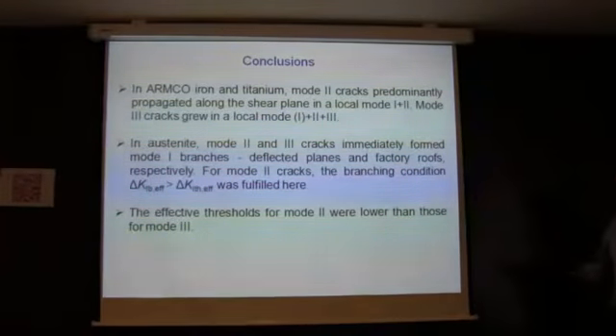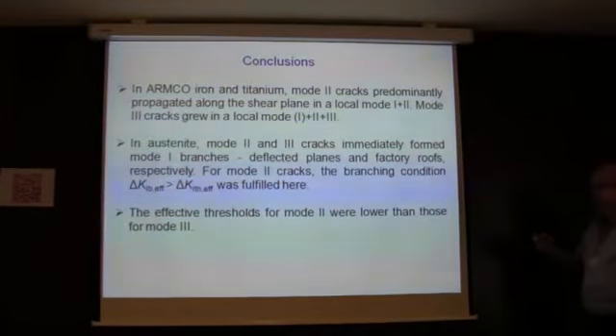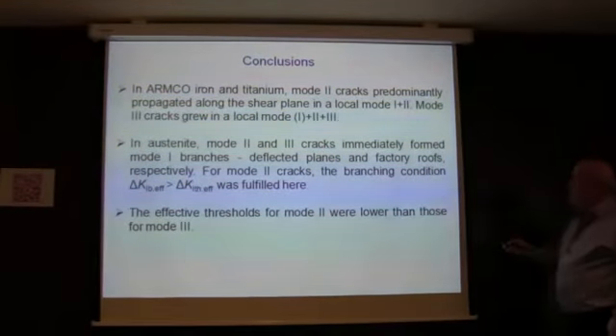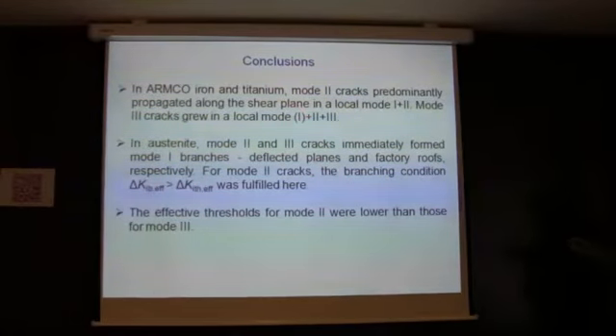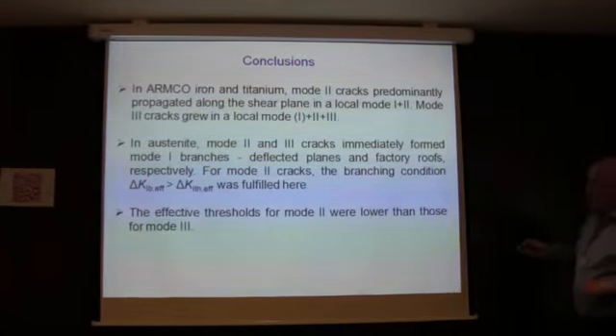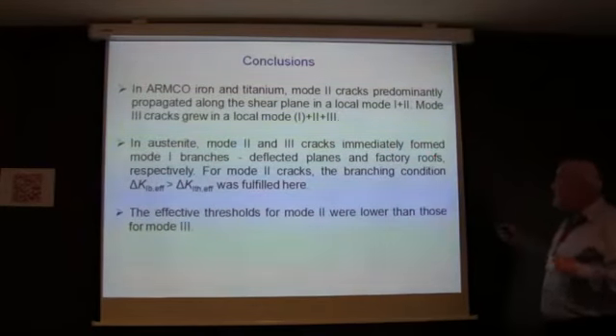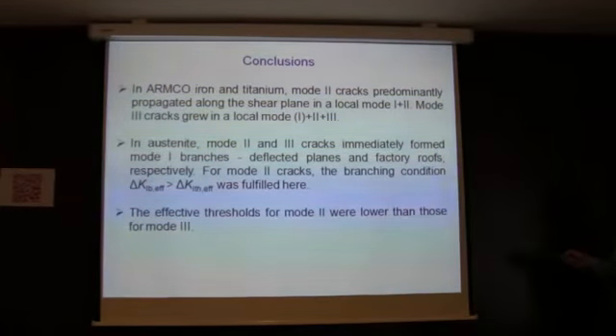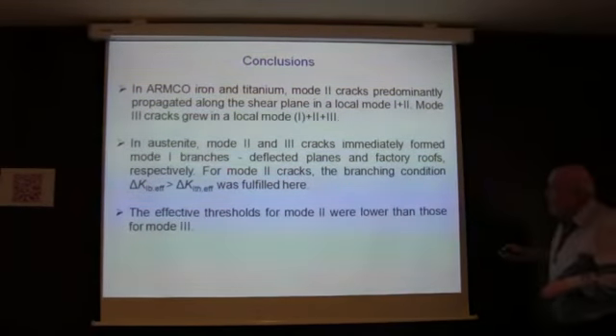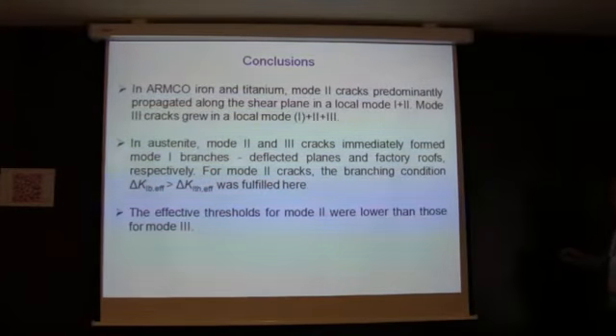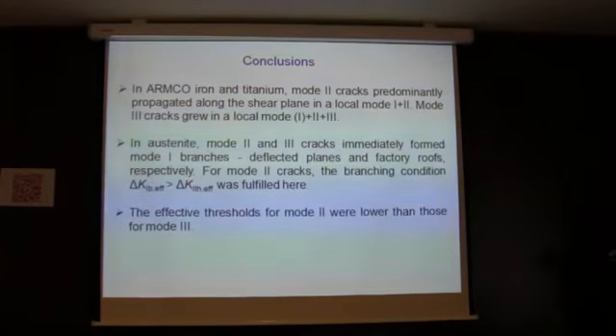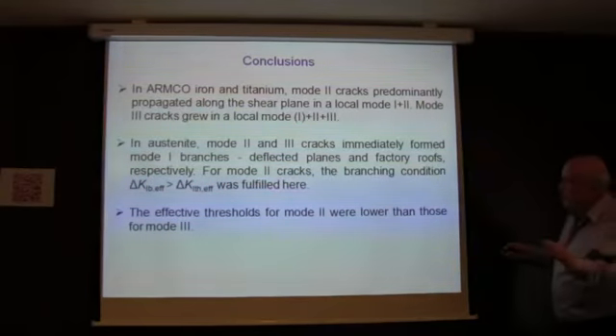Okay? So let me conclude. In ARMCO iron and titanium, mode 2 cracks predominantly propagated along the shear plane in local mode 2, but in titanium the deflections were higher, and mode 3 cracks grew in a local mode 1, a slight 1 plus 2 plus 3 actually. In austenite, mode 2 and 3 cracks immediately formed mode 1 branches, deflected planes and factory roofs, as you could see before. And for mode 2 cracks, the branching condition I was showing was clearly fulfilled here.